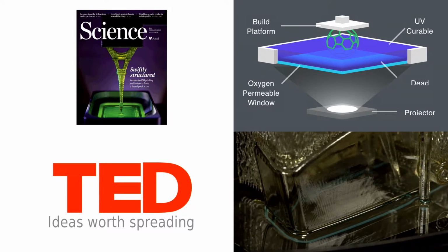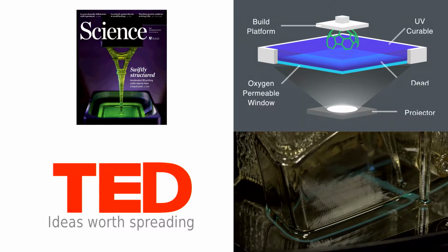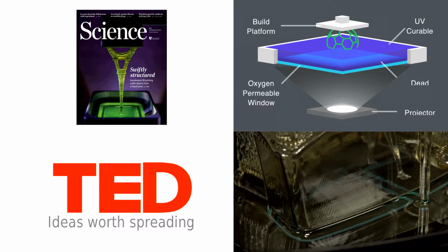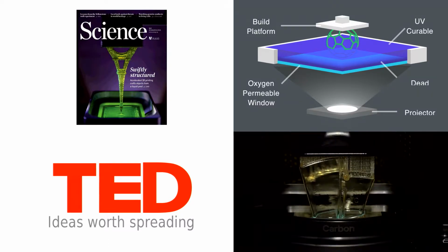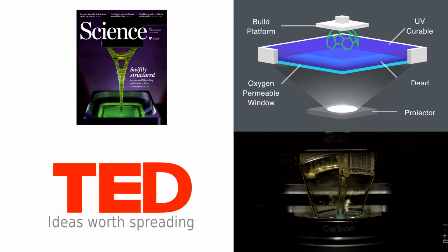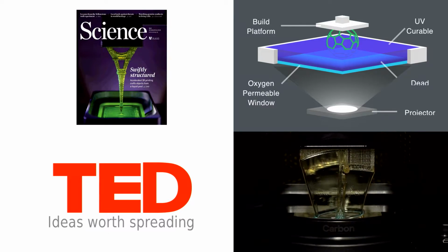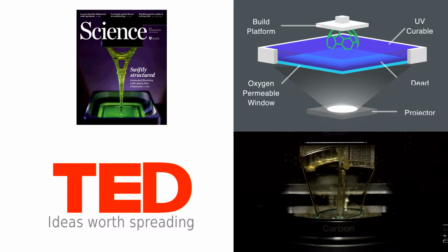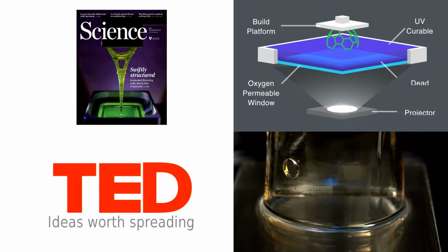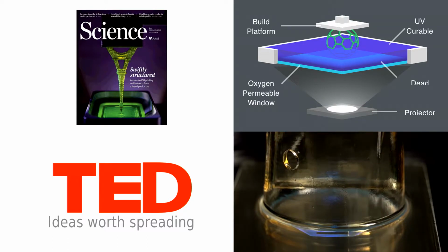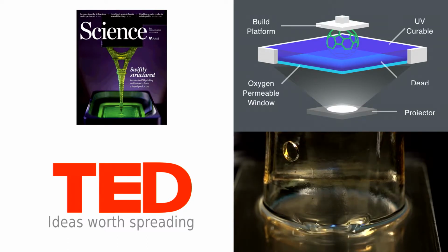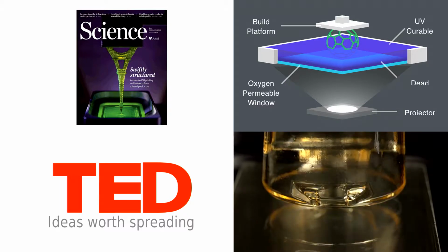That window is not only permeable to light, but it's also permeable to oxygen. Think a contact lens, if you will. Oxygen inhibits polymerization from happening, where light causes it to react. So right at the surface of that window, right where the light is most intense, we maintain a continuous liquid interface all the time that allows us to go in this continuous printed fashion.